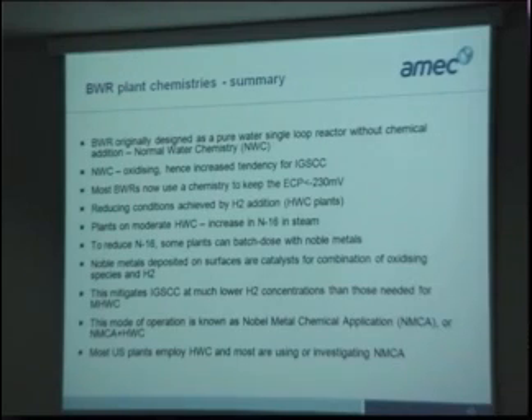As you probably gathered, it's more of an art, balancing the chemistry on a BWR. So to summarise, we have normal water chemistry. You've got oxidising conditions and an increased tendency for stress corrosion cracking. Now we're looking to try and keep our chemistry down to minus 230 millivolts for the ECP. And so we do use hydrogen addition, but plants on moderate hydrogen addition show an increase in nitrogen 16 in the steam, and that's because of the ammonia coming off. To reduce this, some plants can batch dose with noble metals, which I've just mentioned, and that acts as a catalyst for the hydrogen peroxide and other oxidising species with the hydrogen.